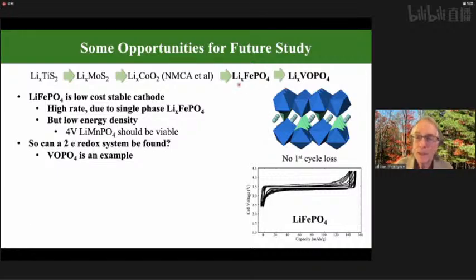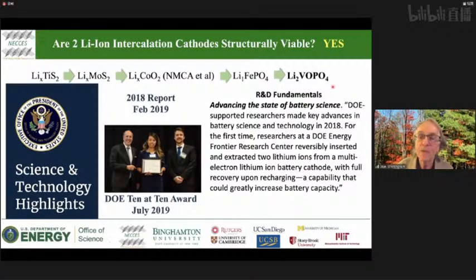So our goal has been to try to build on the thermal stability of this material. This material does not involve oxygen on charging, unlike the layered oxides. But you cannot have iron going to the 4+ oxidation state because it's too high and decomposes the electrolyte. So we've been looking at vanadium. We can go from vanadium 5 to vanadium 4 to vanadium 3. And clearly I wouldn't be talking about this unless we had been successful.